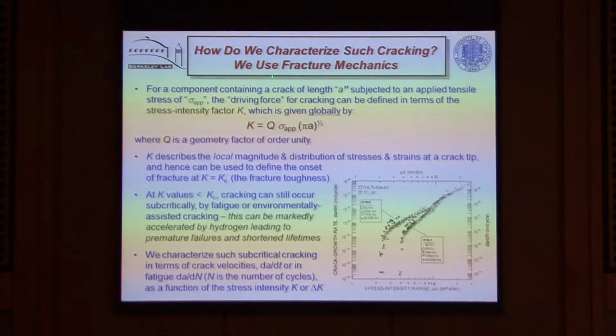So how do we quantify this? Well, this is, of course, very well known to many of you in the audience, but some of you may not. How do we actually quantify how hydrogen can affect the fracture behavior of a material? Well, the approach generally used here is called fracture mechanics, and it's a relatively simple approach. If you have a component which has a crack in it, and all components have cracks in them, and we have a certain applied stress on that crack, we can define something called a stress intensity factor, which is of the form I've drawn here.